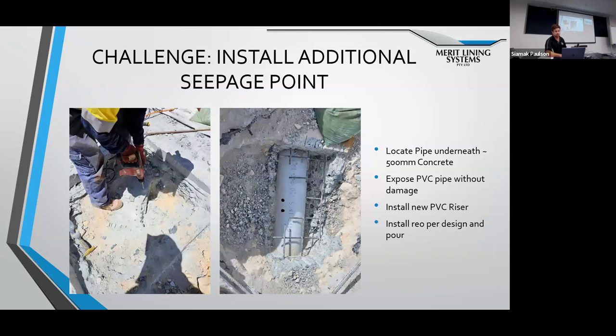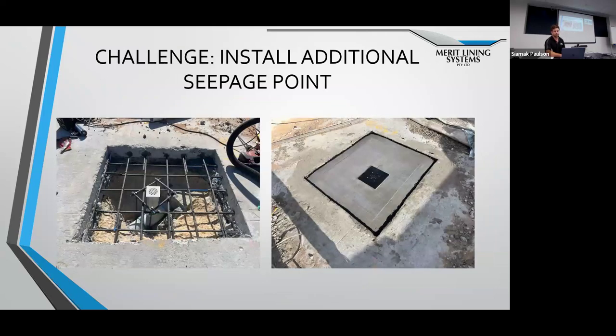Another challenge we had was installing the additional seepage point. We had to locate a pipe underneath 500 millimeters of concrete. To do this, we used a probe, exposed the pipe without damaging it, installed a new riser, and then had to install reo and concrete to finish off the seepage point.